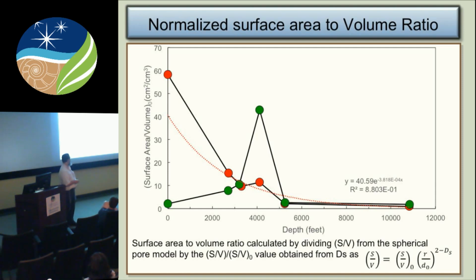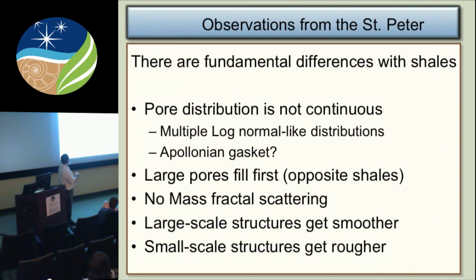Except for this one point, we see pretty much the same scale. This is a depth where there is significant alteration. Something happened to the sandstone at that depth. The sandstone has gone through a number of diagenetic events since its deposition. And there's carbonates and other things that have been deposited in this particular sample. So then if we look at overall what we've seen for the sandstones, we see that unlike the shales, we get non-continuous distributions of the porosity with these multiple log normal-like distributions, possibly because the sandstone itself looks something like an Apollonian gasket in its structure.